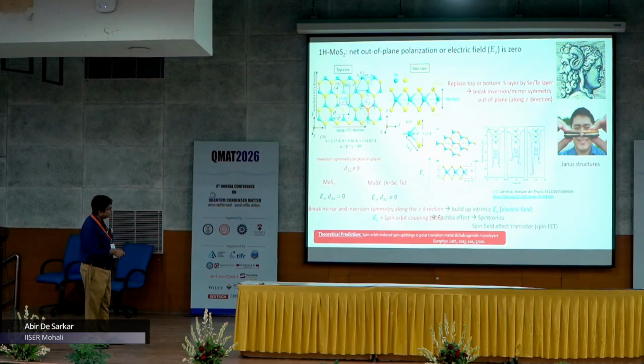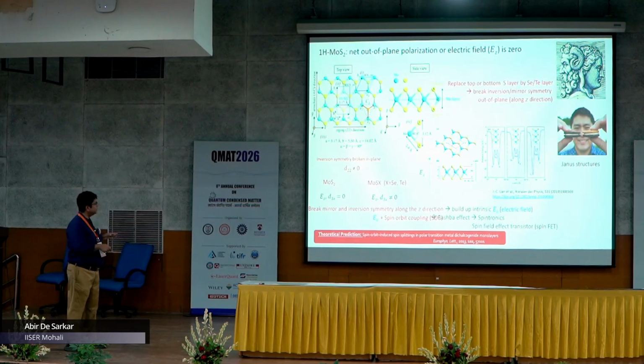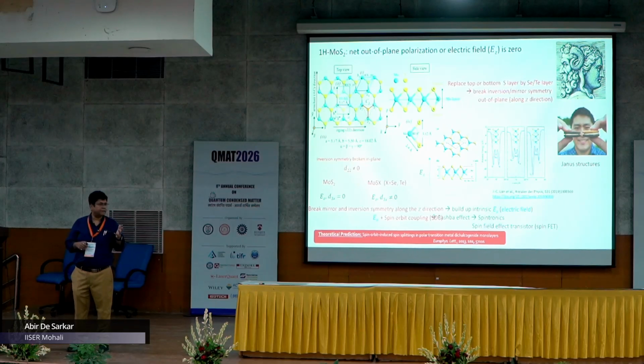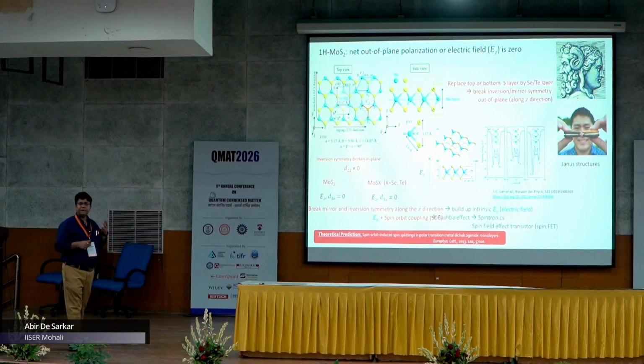This is the pristine MoS2 structure. Here the crystal potential is symmetric. As you turn it into the Janus structure, the crystal potential becomes asymmetric. The asymmetry in the crystal potential builds up an electric field along the z direction, and the out-of-plane electric field, together with the spin-orbit coupling, brings about the Rashba effect, which can be gainfully exploited in spintronics, and that was the motivation behind this work.